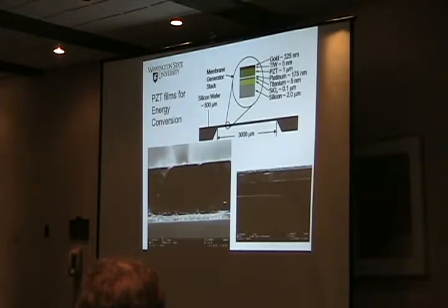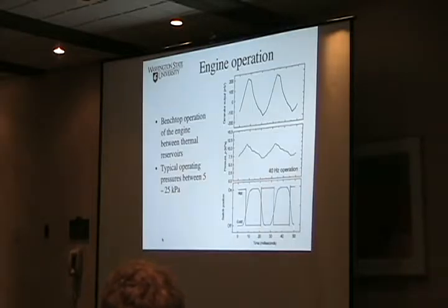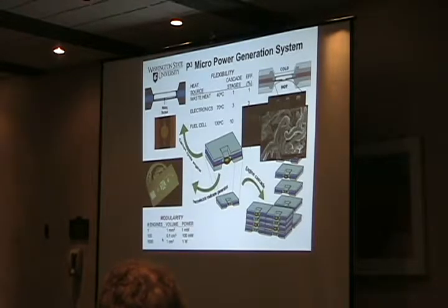So what's the fluid in there? The fluid we use right now is Fluorinert or PF5060, depending on which student's doing which experiment. So with sort of a third of a bar on it, you hardly change its phase transition temperature at all. We in fact don't want to change the temperature. We keep it at its vapor pressure. That's bad for Carnot cycles because it means that delta T for the guts of the engine is very small. We've actually designed this to work over about an 8 degree C delta T.